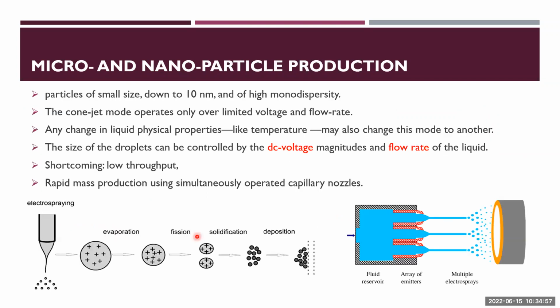The other technology is particle production: micro and nanoparticles, and even millimeter particles, which we call beads. We can produce particles of small size, down to 10 nanometers, with high monodispersity. The cone-jet mode operates only in limited voltage and flow rate. So during the development of the formulation and the process, we need to find the best combination of flow rate and high voltage that gives a stable cone-jet. Basically, we need a stable cone-jet to get good and reproducible nanoparticles.